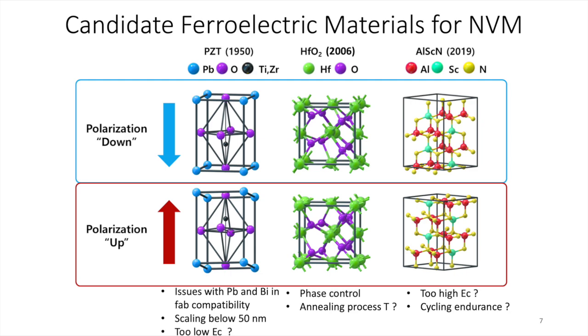You cannot scale them below 50 nanometers in thickness, and their coercive field, so to speak, is too low, such that minor electrical fields or current pulses can lead to their depolarization or changing of the bits, or bits can flip. In other words, it will introduce errors in the stored data.